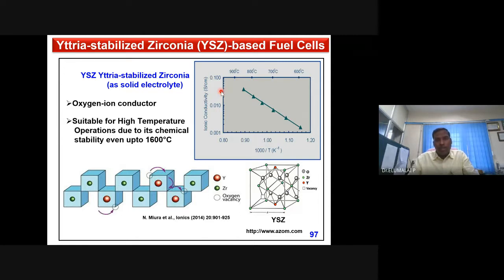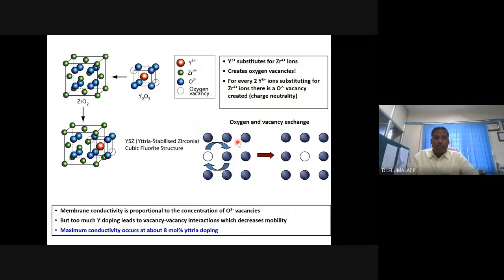Scandia also can be used. Scandium doped, you can get very high conductivity, but it's also very expensive. So practically, it is not feasible. So yttrium offers relatively high conductivity at high temperature and relatively less price. So yttria stabilized zirconia is used. This material is commercially available. Typically the doped concentration of yttria is 10% or 8 mole percent. Okay. The optimum concentration is 8 mole percent. Yttria doped zirconia is the electrolyte used in this SOFC.